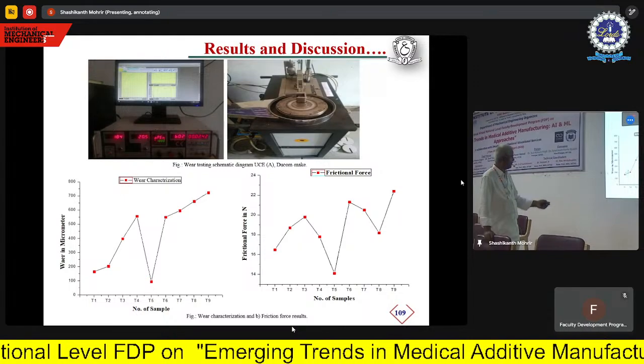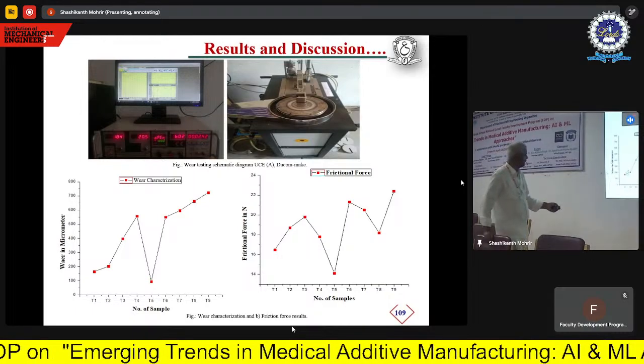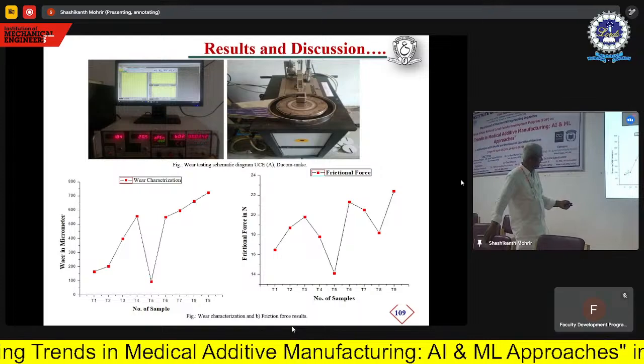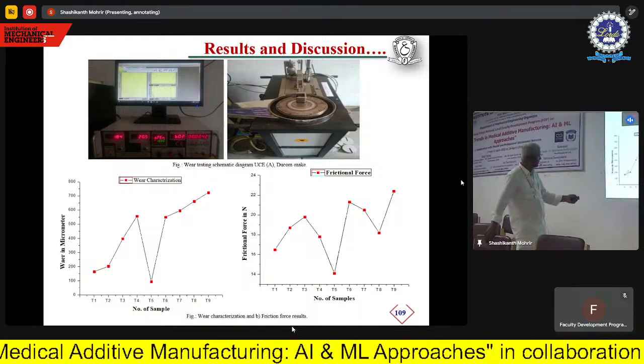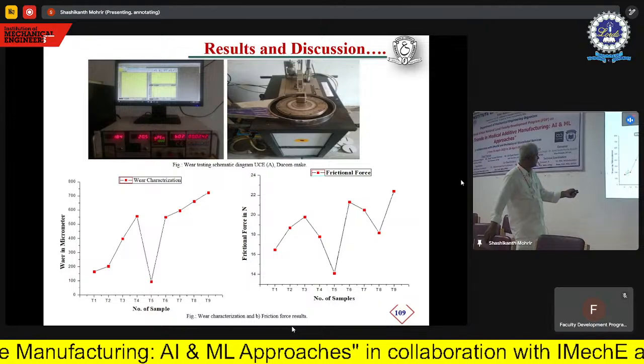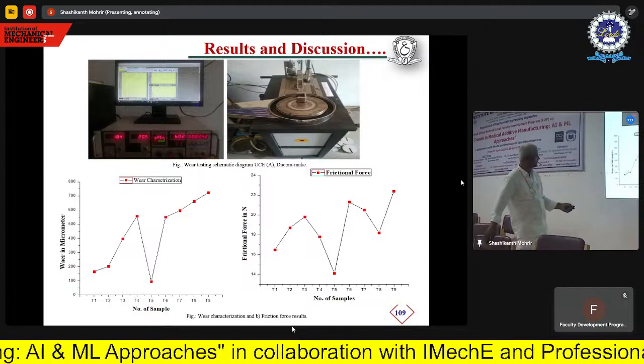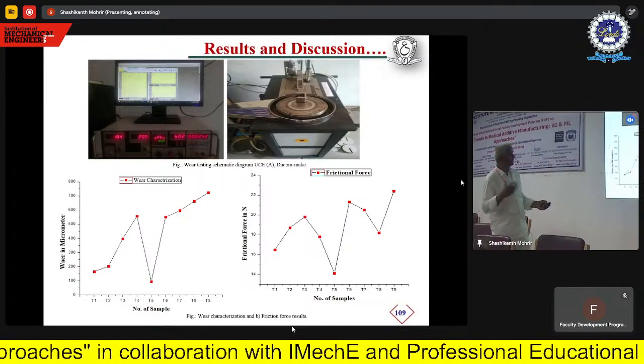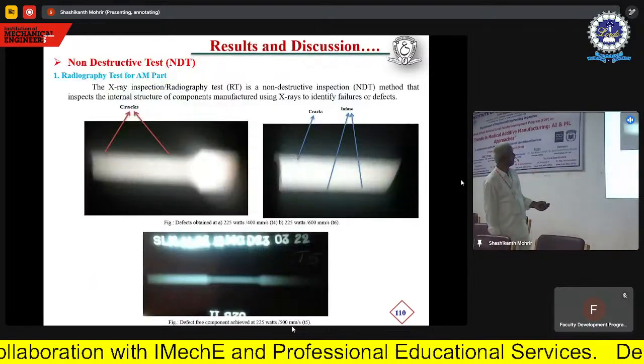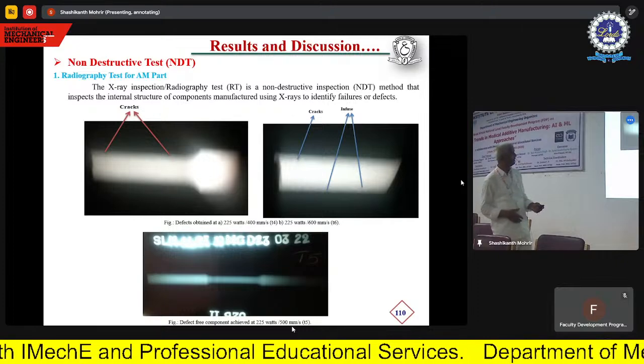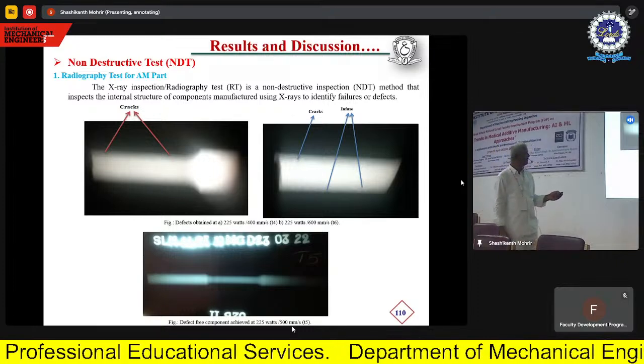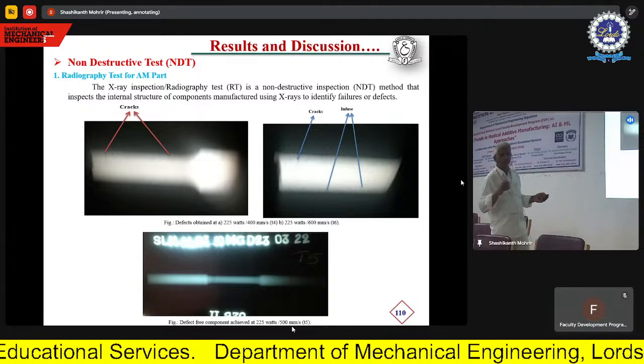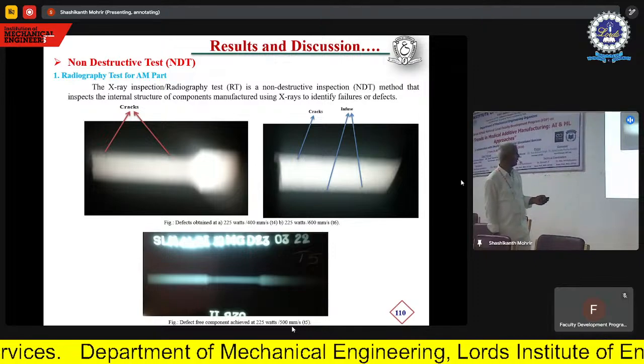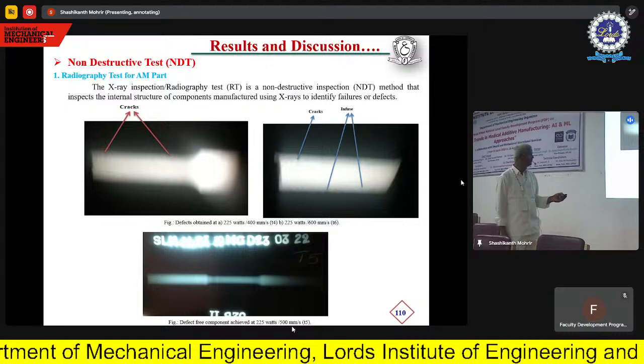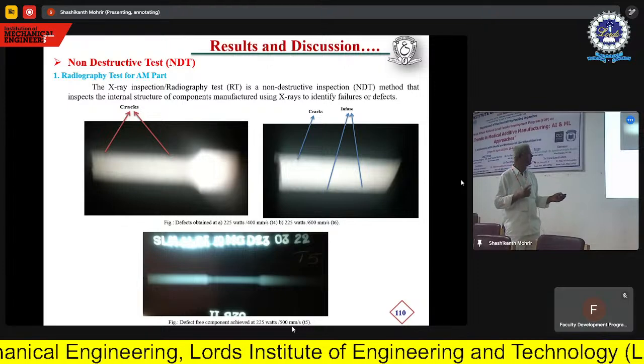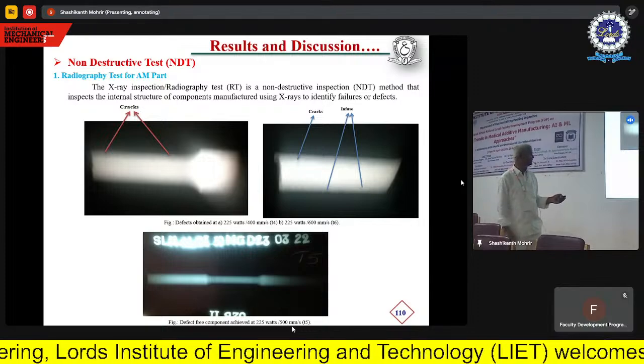T4, T5, T6. So this gives a proper density, but even this is unpredictable, and 2 are proper, and another one is at the bottom. So some interpretation, some sort of discussion is required. And radiography, you also have to tell. Radiography gives internal damage, internal full depth. So we have to do non-destructive testing. We have to see whether the whole volume of the printed specimen is defect free.